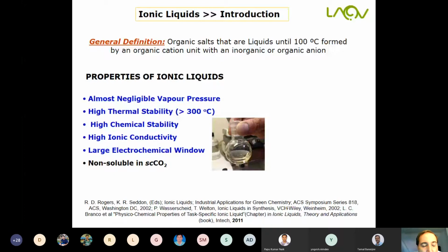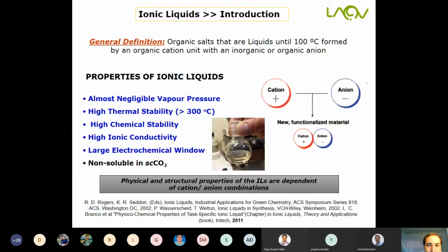These two properties can be important for some applications in energy, and also the insolubility in supercritical CO2. Supercritical CO2 that I mentioned before can be considered as a green solvent, and this combination of supercritical CO2 and ionic liquids can be very interesting because it's possible to use supercritical CO2 to remove selectively some compounds from ionic liquid media and not to remove the ionic liquid. And this can be a clean and efficient extraction process.